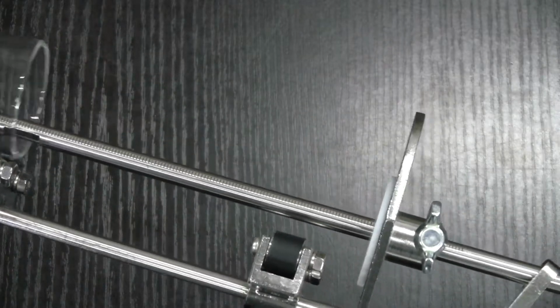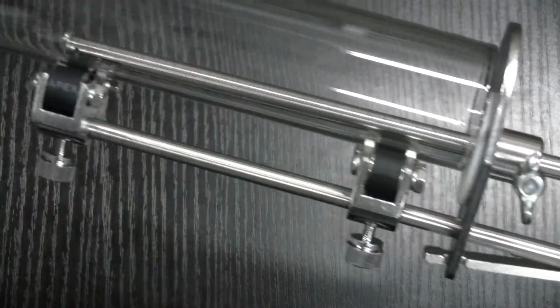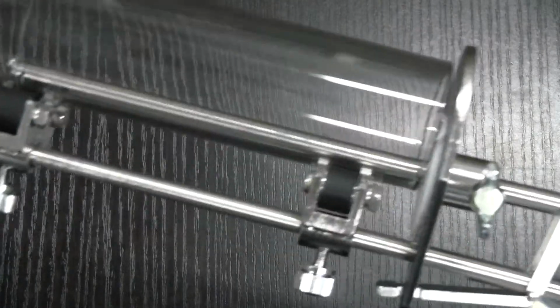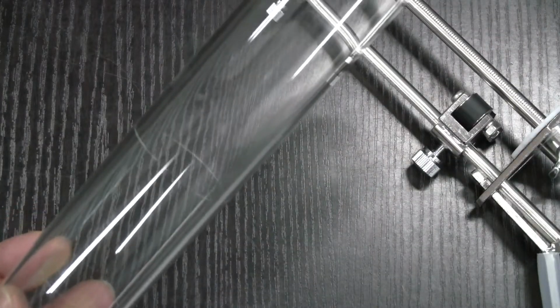5. If the fracture line is white and looks like a score mark made with a conventional glass cutter, you have applied too much pressure. A perfect internal fracture line is so thin it's hard to see. It is a shiny crack that reflects light but has not crushed the glass and left a white line. A perfect fracture line is easier to see if held up to the light.